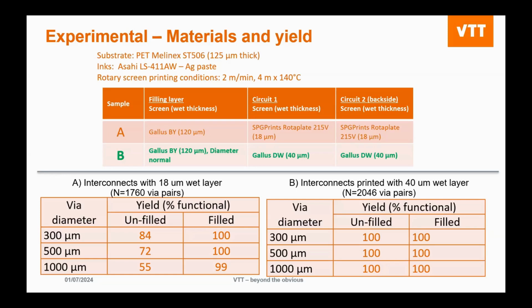The main message I want to give you is that depending on the screen parameters, the wet thickness of the ink, and whether or not you fill the via hole, it'll have a different effect on your yield. So for instance, what does unfilled mean? Unfilled is without the additional via filling step. You're just printing the circuitry on side A and side B, and then the via filling will just be from the printed traces. So it'll just inflow into the via.